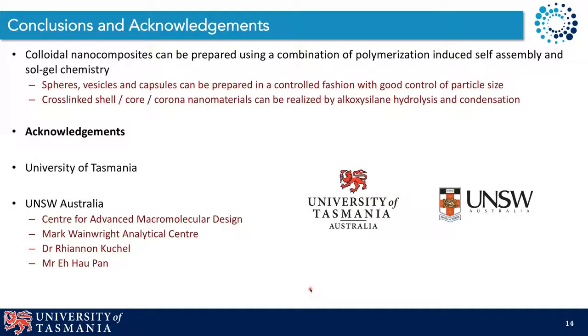So to conclude, I hope I've demonstrated that we can prepare colloidal nanocomposites using a combination of polymerization induced self-assembly and sol gel chemistry, where spheres, vesicles, and capsules were prepared in a controlled fashion with good control of particle size. And by using that as a resulting polymer nanostructure, we can then functionalize the surface with other alkoxysilanes.